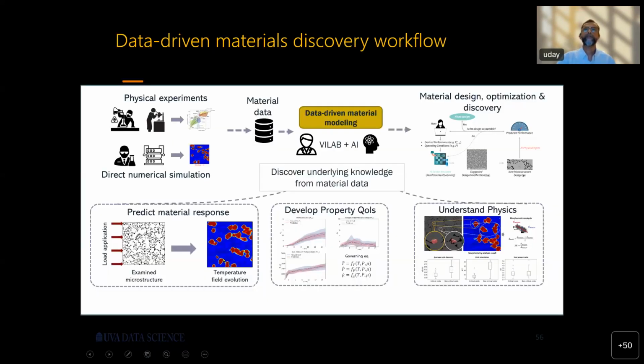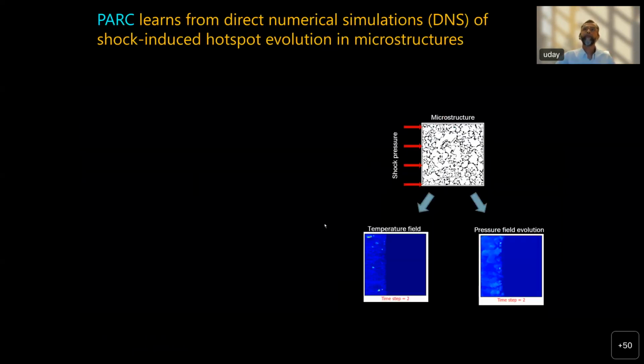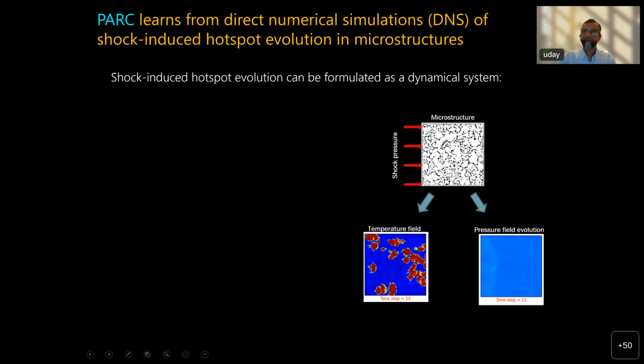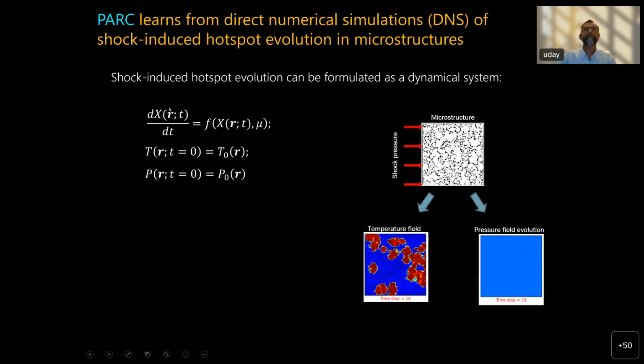And as I said, PARC fits into this overall framework as a data-driven modeling entity. So this is the DD model that we're using in the larger materials design optimization and discovery framework of MatterIQ. So the idea behind PARC is that we are going to formulate the shock-induced hotspot evolution as a dynamical system. That is, we pick this variable x from the physics of the problem, and in our particular case, we pick x to be a function that consists of a vector of the temperature of the hotspots, the pressure in the domain, and the microstructure, because the microstructure evolves. So it goes from voids to void collapse and then eventually to hotspots.